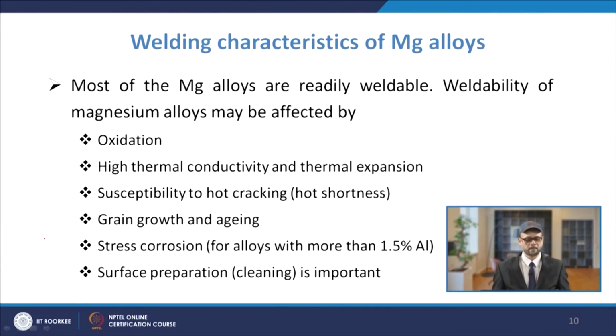If we discuss the welding characteristics of magnesium alloys, most of the magnesium alloys are readily weldable, but they can be affected by oxidation, because oxidation of magnesium and its alloys is very rapid. When heated to the melting point in air, it readily gets oxidized. There may be burning and fumes, so it is considered very challenging. You normally try to have an inert atmosphere and use suitable fluxes in those cases.